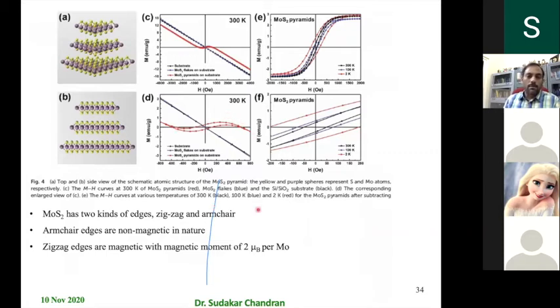And that can happen even in the nanosheets, what we discussed. So you have edges that are magnetic in nature, and there are edges that are non-magnetic in nature. So there are two kinds of edges you will find: zigzag and armchair edges. The armchair edges are non-magnetic in nature, whereas the zigzag edges are magnetic, and they give 2 μB per Mo magnetic moment. Okay, so enabling magnetic properties.